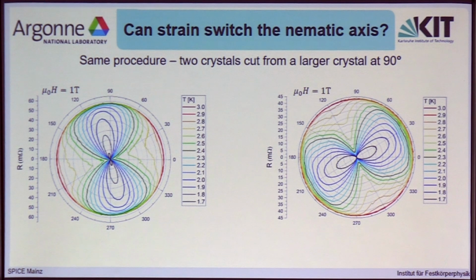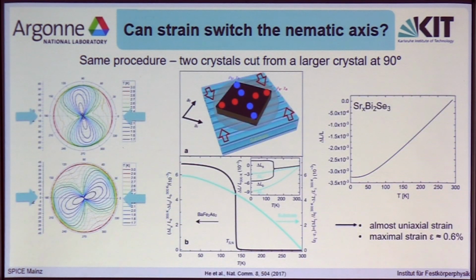We put them next to each other, and we mounted them on a glass fiber reinforced plastic. Now, what's special about this glass fiber reinforced plastic is that it has a very anisotropic thermal expansion along 2 different directions. So you can see here thermal expansion measurements that have been done in the group of Christoph Meingast at KIT. You can see it has a low contraction direction and a very high contraction direction, and they're actually different by a factor of 3.